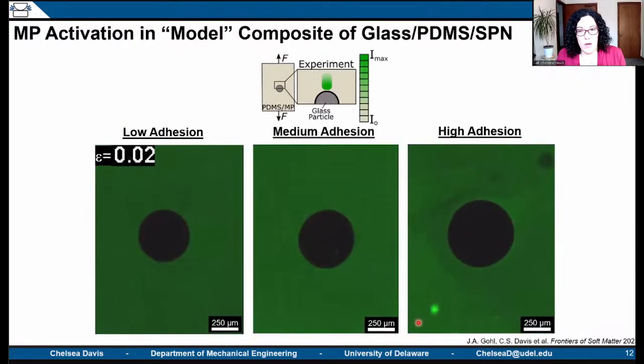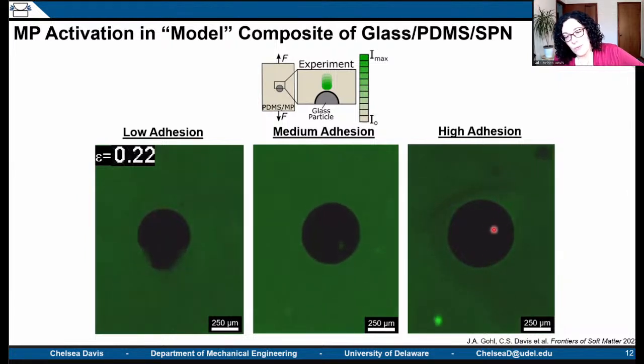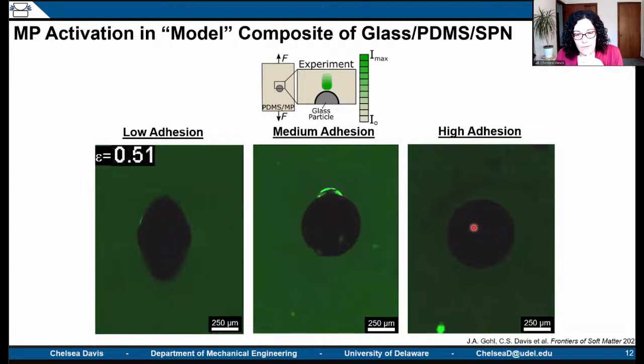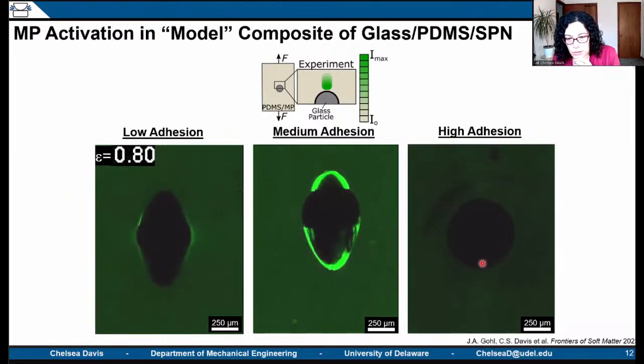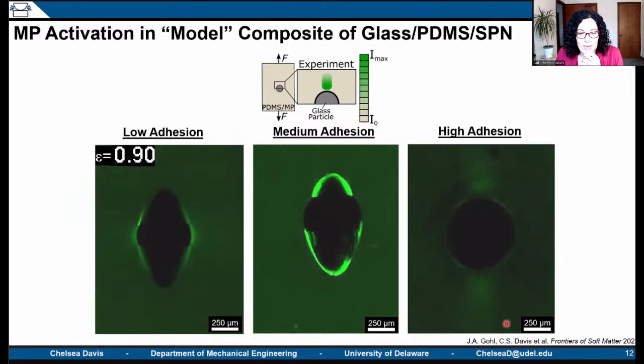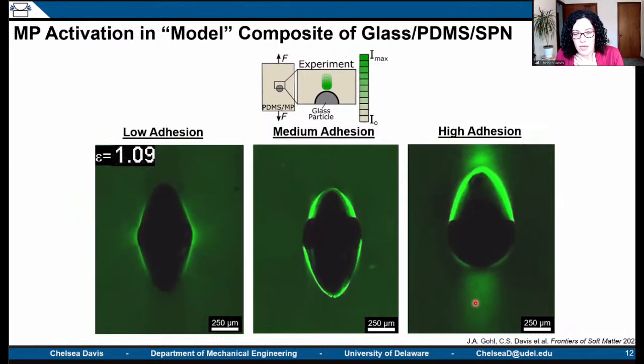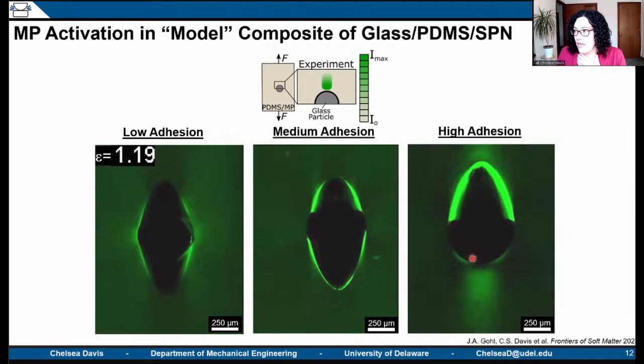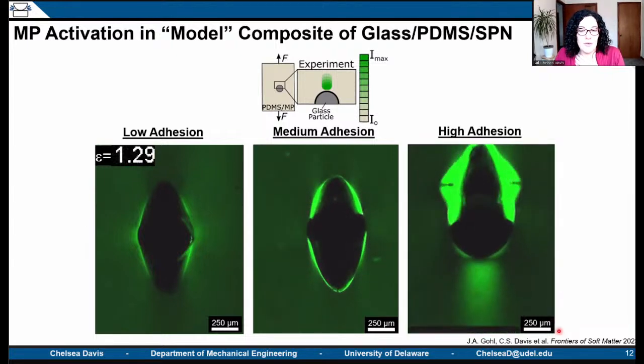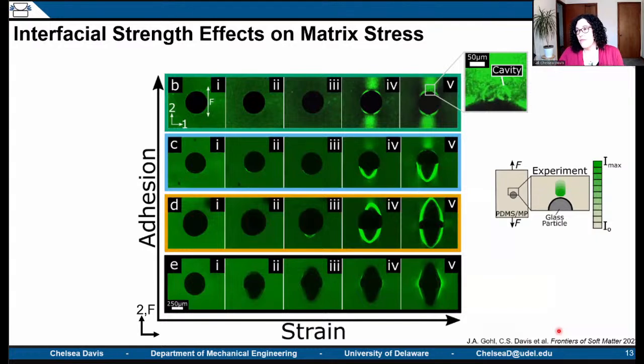Let me try. For the high adhesion case, what we were really going for, this was not the highest adhesion case. We improved our method a little bit beyond that. But if we keep going, we're already at 40, 45, 50% strain. And you can see the interface is starting to fail in the two lower cases. But here, what isn't it going? There we go. You can start to see stress happening around 90, 100% strain. And we're going to get a Gent-Park debonding on one side, but we really care about this right here. This is going to allow us to perform the calibration that I showed you on the previous slide.